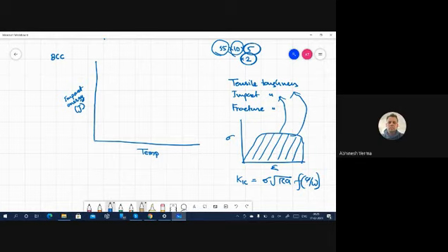So fracture toughness is a measurement of toughness, but it requires a crack to begin with. That's the idea of fracture toughness. For impact, you don't have to have a crack, it's a notch. There is a difference between a notch and a crack, although at some scale both are the same. A crack is a sharper notch, a very, very sharp notch, or you can say that a notch is a very blunt crack. In that way a hole would also be a crack, but we can't use a hole as the definition of a crack and fracture toughness. So fracture toughness is a different toughness.